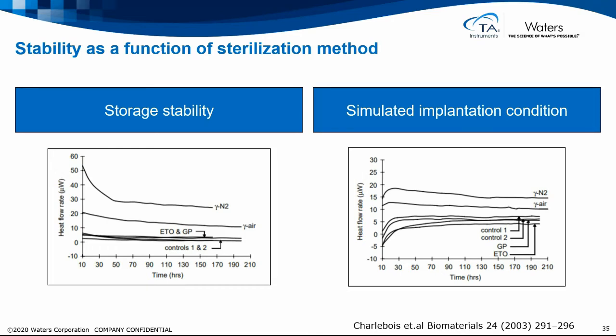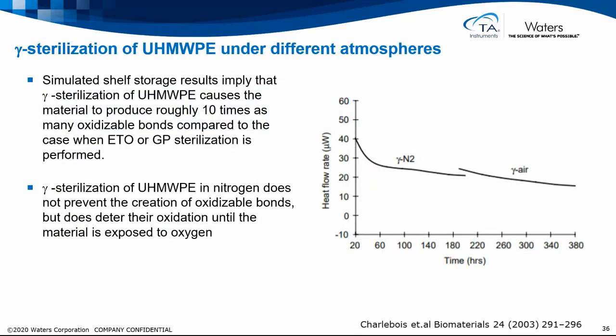So how can we explain the differences here with the different gamma irradiation? Well, we can do the test under different atmosphere, and simulated shelf storage results will imply that with gamma sterilization we get roughly 10 times as many oxidizable bonds compared to the case when you use the ETO or GP sterilization. But sterilizing in nitrogen does not prevent the creation of the oxidizable bonds, but it will just push the oxidation until the material actually is exposed to oxygen. And at the implantation time, the material will be exposed to oxygen, if not prior to that. So this can be seen if that is taken into account, and they almost fall together on the same line.